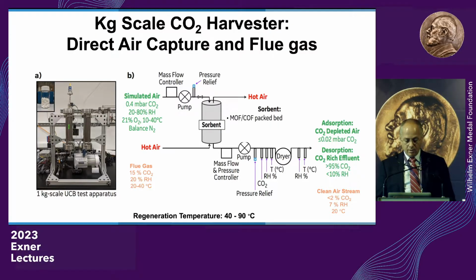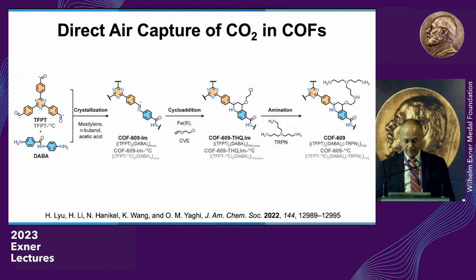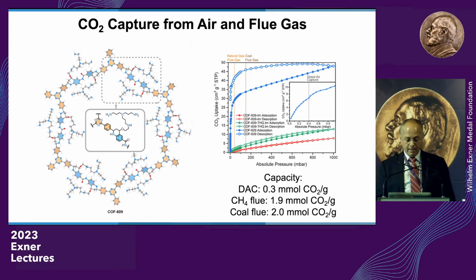We have also been working on COFs with very strong backbone, such as these, and functionalizing those COFs with amine units. And these amine units take up from air 0.3 millimole of carbon dioxide per gram of material. And for flue gas from natural gas, 1.9 millimole CO2 per gram, and from coal, 2 millimole of CO2 per gram. Okay, so it's great for this, and for DAC, it's already taking up 0.3 millimole CO2 per gram. That's significant. And our target is to get close to 1 millimole from air. If you can have a material that takes up 1 millimole of CO2 per gram, and it can cycle 100,000 cycles, then you can commercialize this material, okay?